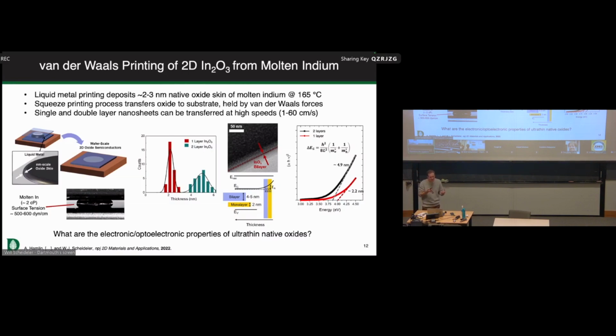So why would we want to do that for a material like indium oxide? Well, indium oxide is a little bit peculiar. It displays surface accumulation. It is natively very conductive because of a lot of the intrinsic oxygen vacancy defects. So being able to make it thin is potentially useful as a semiconductor because it means we can also electrostatically gate it. So we can put it in structures like a thin film transistor where we could take advantage of that.